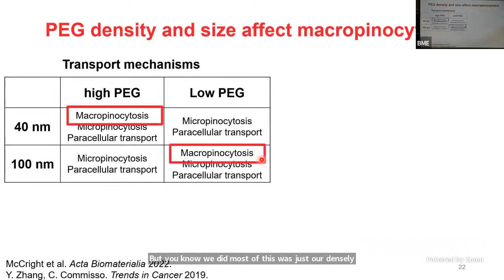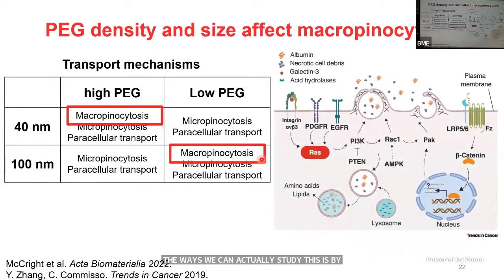So one of the big questions we have at the moment is, what's going on with macropinocytosis? We'd expect that the surface chemistry is probably the main driving factor, but it seems the trends are actually kind of opposite, depending on the size of the particle with respect to the surface chemistry. Macropinocytosis is rather complex, and it often is initiated by some initial binding to a receptor on the cell. This can be initiated through things like albumin, but also PDGFR, EGFR. There are a lot of different receptors that will start the activation of macropinocytosis.